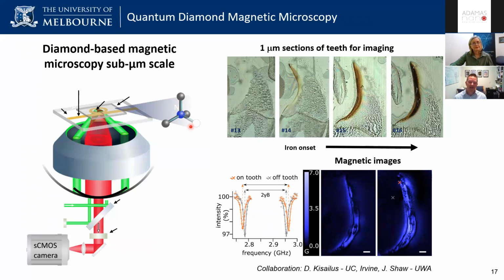But having said that, we also do work where we apply random background fields and look at all of the orientations at once. So instead of these 2 peaks, you see 8 peaks, 2 peaks for each NV axis. Typically the contrast is a little bit less, so your magnetic sensitivity is a little bit less, but it means you can do it all in one go. That would be more like what you would do with the nanodiamond. You don't know what the axis is, but it might be random and you might be able to resolve the 8 peaks, and then you could do it that way.